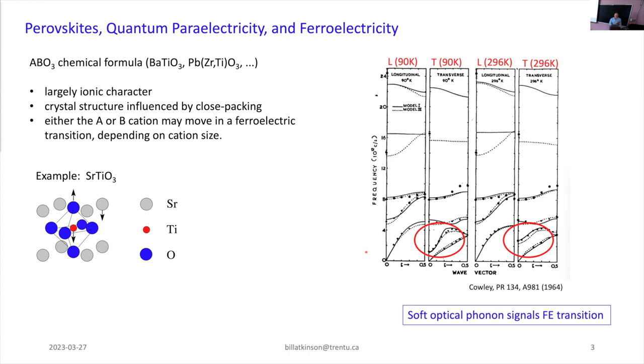And on the right here, I'm showing you old neutron data from Roger Cowley from the mid-1960s. And you're seeing two temperatures. On the left, it's 90 Kelvin. On the right, it's room temperature. And you're seeing longitudinal and transverse branches. And I've circled the relevant mode there.